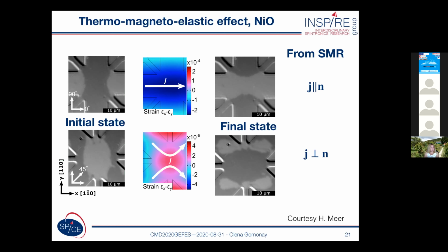However, if we change the geometry of the electrodes and we apply current which flows at 90 degrees, as shown in the lower panel, then the distribution of strains is quite different compared to the upper slide. But the direction of the current in the central region is the same. And in this case, we see switching of the Néel vector, which is perpendicular to the current direction. This type of switching is consistent with a thermomagnetoelastic mechanism, but could not be explained by spin-orbit torques.